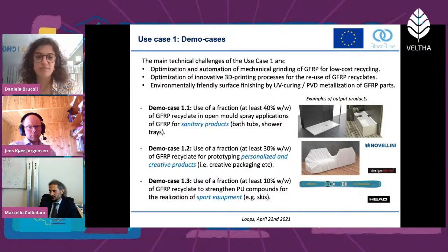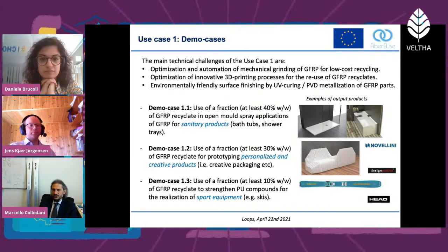The first strategy, which is giving origin to these three demo cases, is based on mechanical size reduction processes. We take the post-use component, we shred it, and we form a continuous and homogeneous stream of granules of glass fibers and resin. We then reprocess this fraction into new products that embed this fraction plus virgin resin and virgin fibers. With this strategy, we have produced these sanitary products, bath-use and shower trays with a spraying technology, and with at least 40% of recycled material inside.